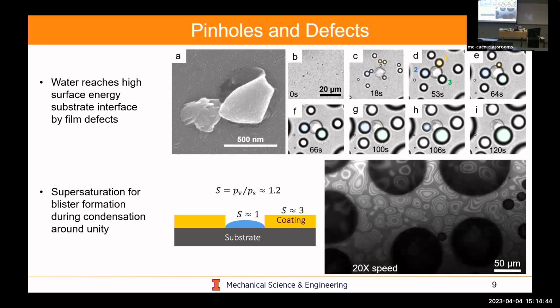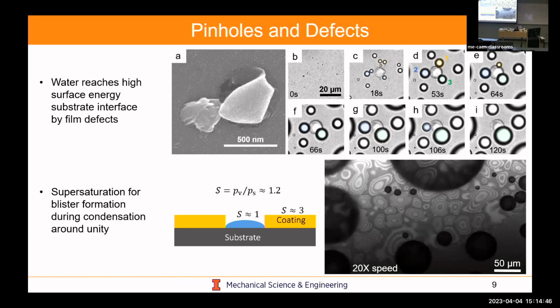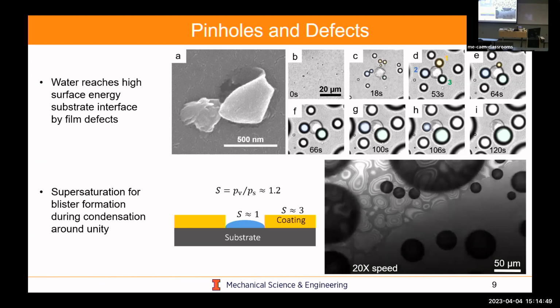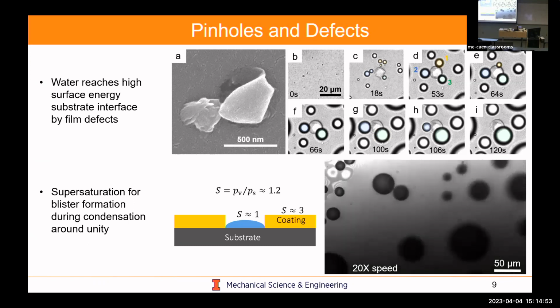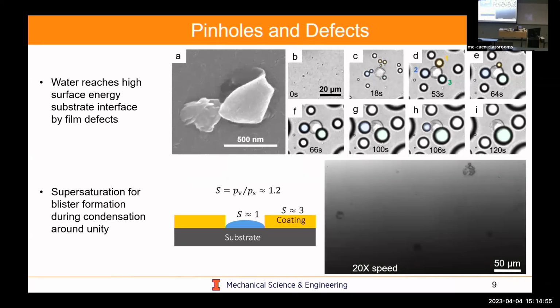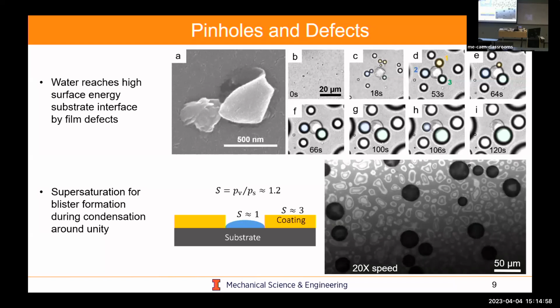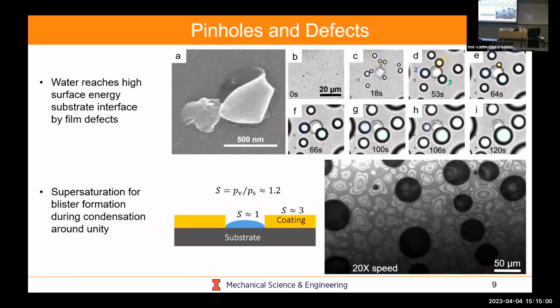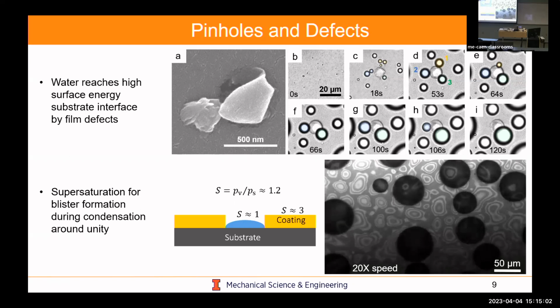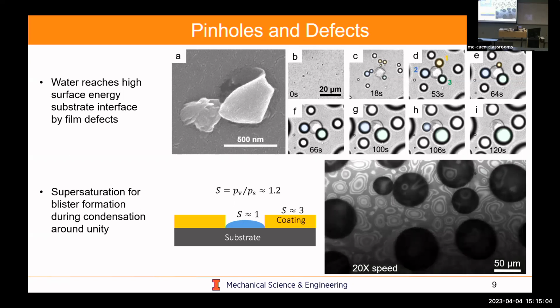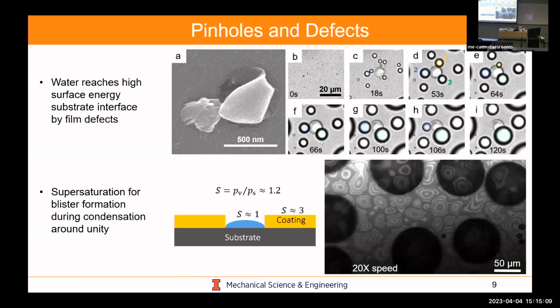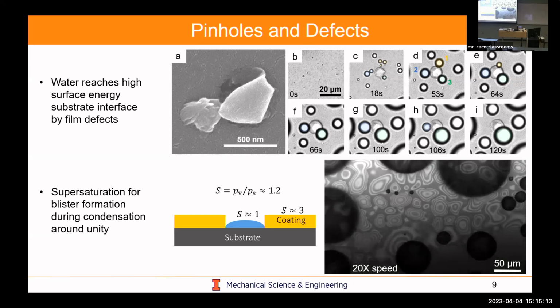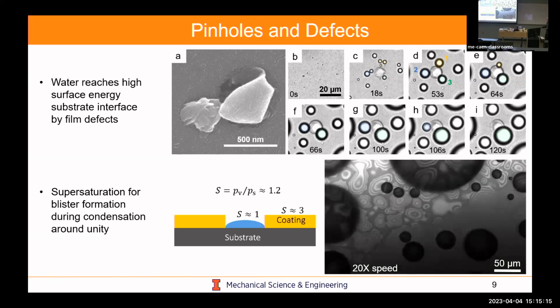The other way we actually observed this was when you look at when these blisters grow. So this is a time-lapse image, from B to I, you see the blister grow right here, and these are droplets around it, and what you'll actually see is cross-communication between droplets. So this droplet here, number one, will enter the blister, but then it'll actually be injected into one of these two droplets here. So if it keeps growing, you'll notice the blue droplet will enter the blister and then enter this droplet here. And so there are definitely pinholes within this blister, which actually cause communication between your substrate and your liquid just growing on top.